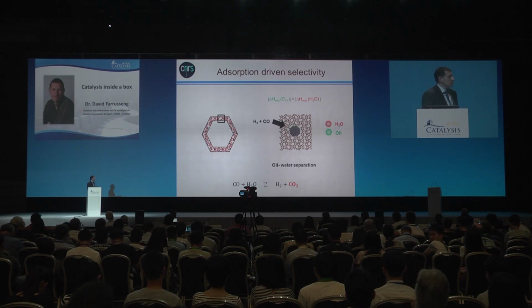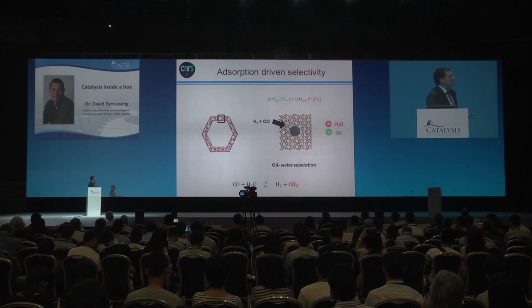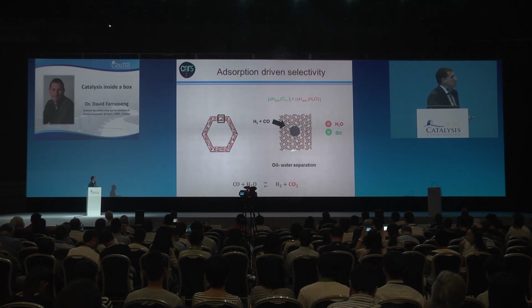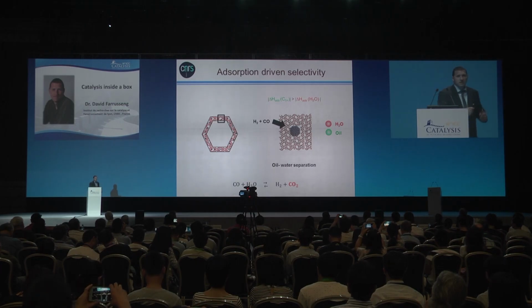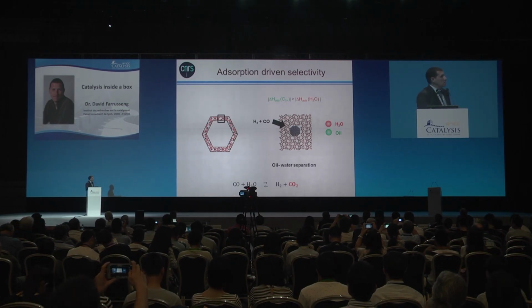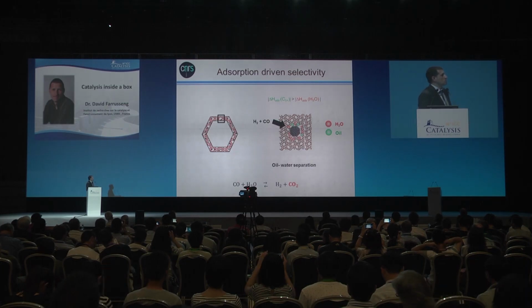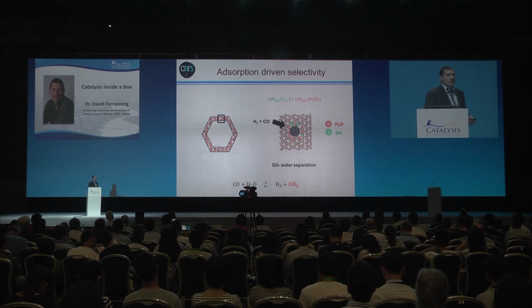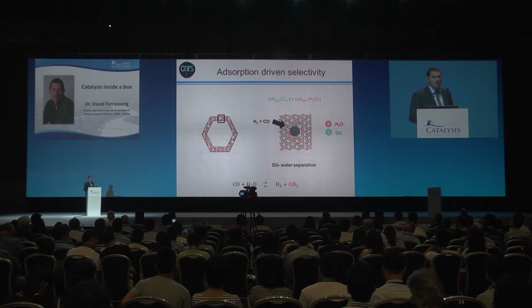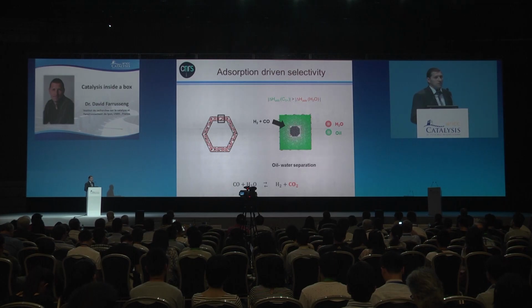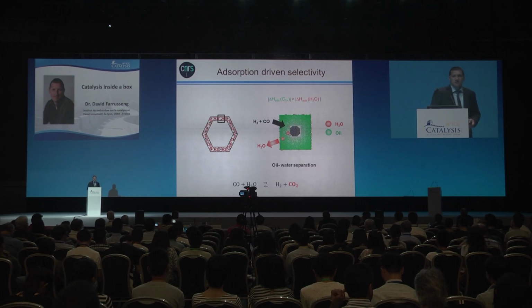So in the scheme of that, we have here an iron nanoparticle embedded in this very narrow and very thin membrane shell. H2 and CO would go across the membrane, react, and produce water and oil, but water and oil cannot be there together for long. They have to separate. Oil and water don't like each other. So what will remain in the pores is indeed the oil, and the water will be pushed out. The winner in this case is of course the oil.